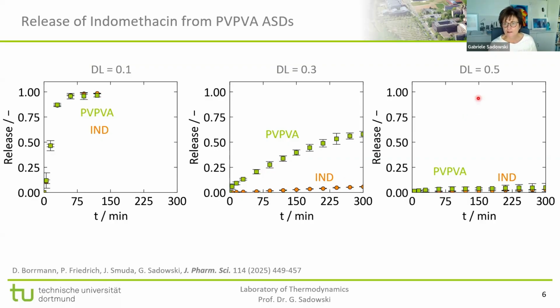And that gets even worse if we further increase the drug load. So if we are at 50%, that means now 0.5, it's getting worse and worse. So actually, none of the two components is releasing anymore, which means the tablet didn't dissolve, because 100% of the two components would be up here, and we are, you see, far below even 5 or 10%. So the question is, what happens here? What is the reason for this? And this is where we started to work on that.